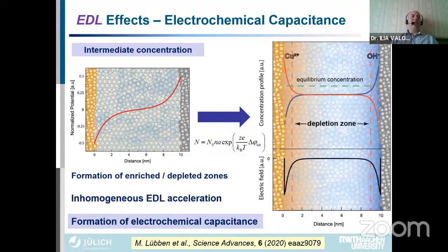The situation is interesting when you have the intermediate concentration, which is neither too low, nor too high, because in this case, the internal electromotive force results in splitting the charges. So they're not homogeneously distributed within your material, but they form enriched and depletion zones, which also change the device behavior, and also they form some kind of so-called electrochemical capacitance. So additionally to the classical physical capacitance that is in fact determined from the matrix, you can also have intrinsic separation of charges, which will lead to formation of electrochemical capacitance.